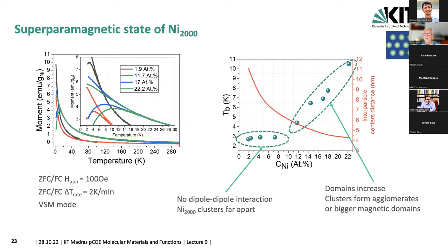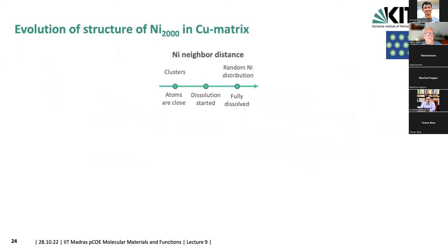And when we talk about magnetic agglomerates, that doesn't mean that we have really clusters already touching and forming agglomerates, which could, of course, also happen. So here is basically the evolution of the structure of nickel 2000 atom clusters in a copper matrix. So if you look at the nickel neighbor distance, so of nickel-nickel pairs, you can distinguish them.